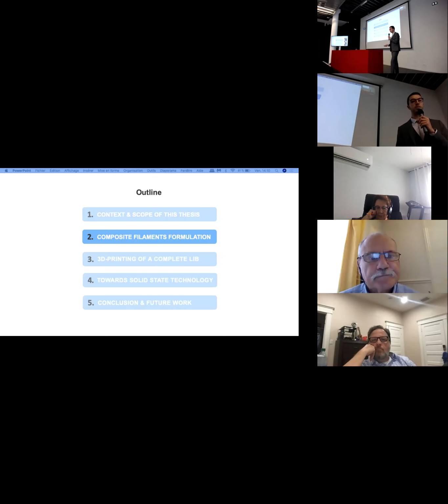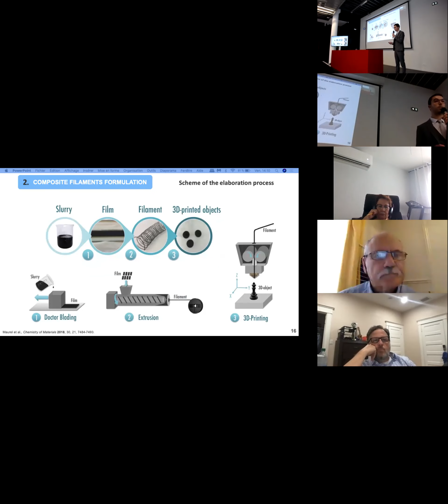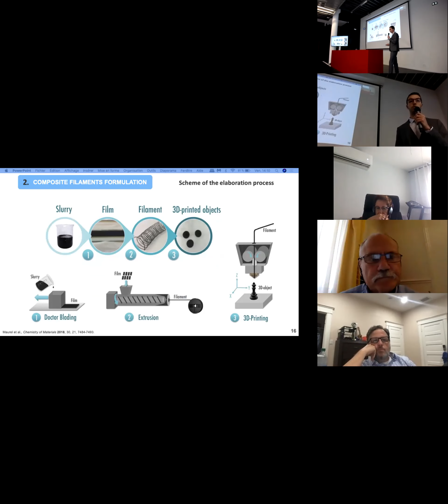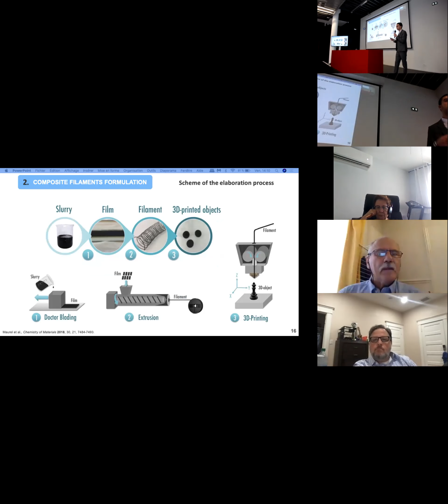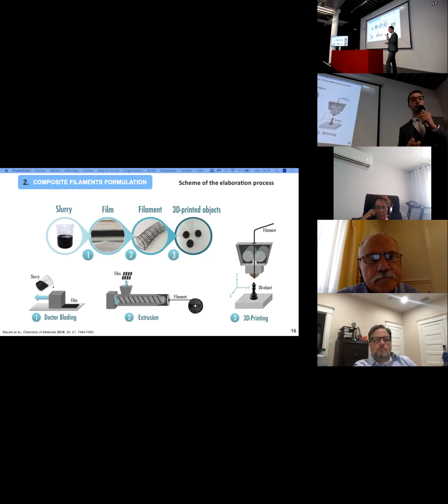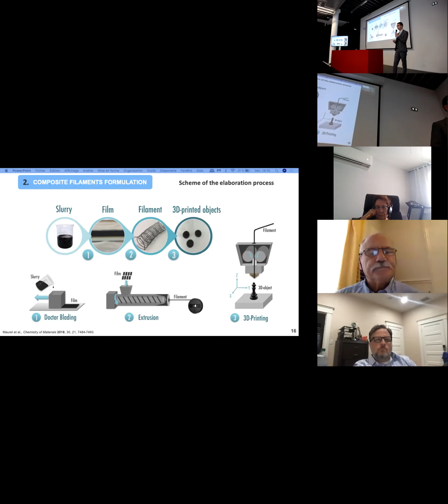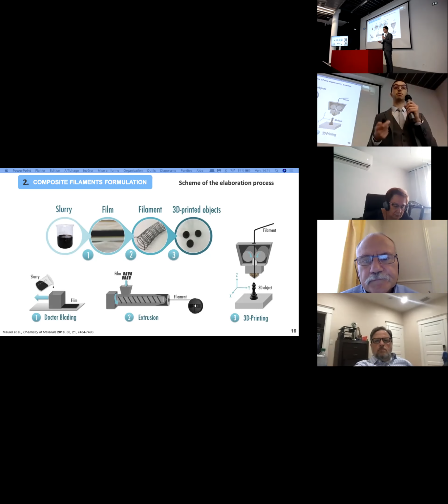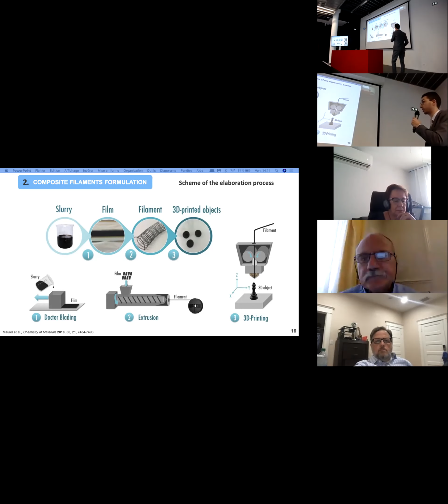So we started first of all with the composite filament formulation. First, we established an elaboration process. Here we decided to use a solvent in order to combine both the polymer matrix and the active materials. That was not ideal, but at least it was easy. I mean, it was easier to have homogeneous samples at the laboratory scale. After we have a homogeneous slurry, we perform tape casting, and after evaporation of the solvent, we obtain a classic film. This film is divided and cut into tiny pieces and used as a material source to feed the extruder. With this extruder, we then obtain, after extrusion, classical 1.75 millimeter filaments. This filament is finally used as the material source for the 3D printer in order to print many objects, such as these 3D printed discs.